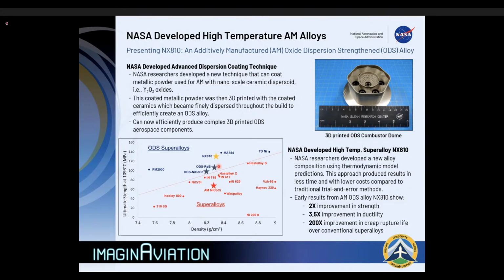And you can see just with this first try at a new composition, comparing it to that initial alloy composition of nickel cobalt chrome without oxides, we've basically doubled the strength at 1100 degrees Celsius. But what you can't see from this graph is that not only is the strength double, but the ductility is almost 3.5 times better than the nickel cobalt chrome without oxide. And so you can imagine it takes significantly more energy to actually break a component made out of this new alloy compared to the nickel cobalt chrome without oxides.